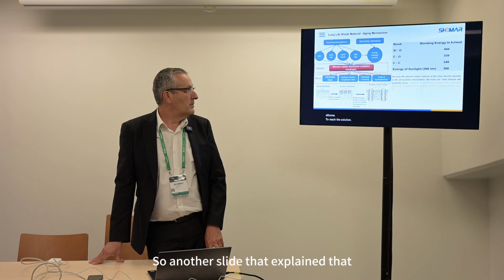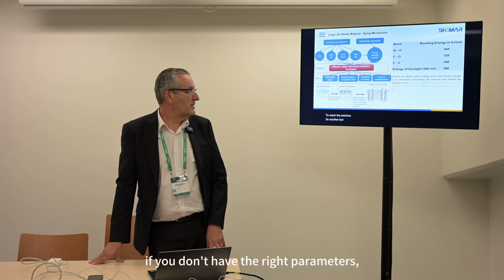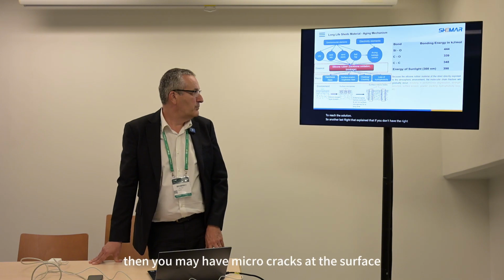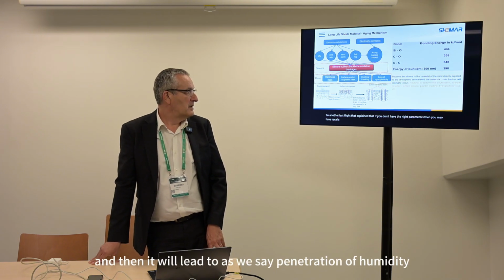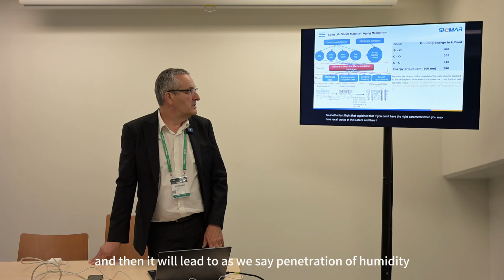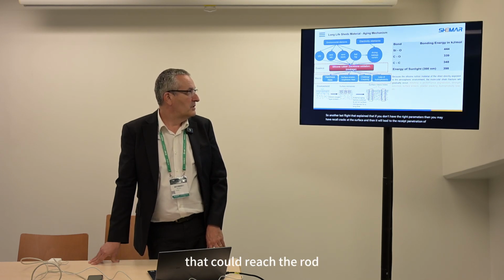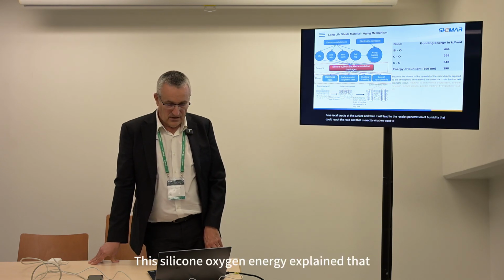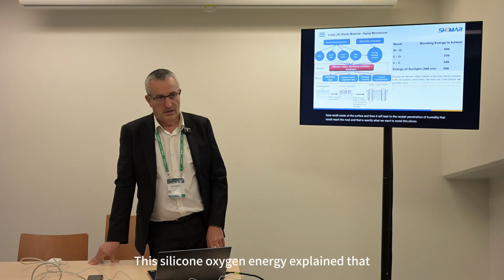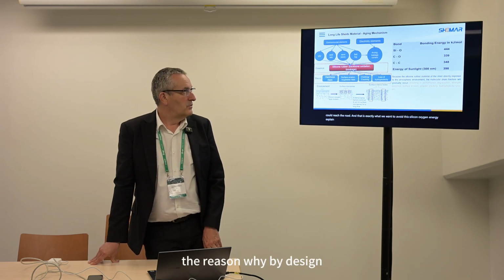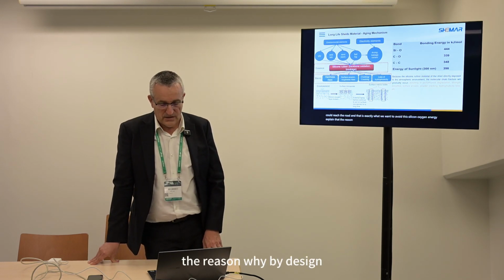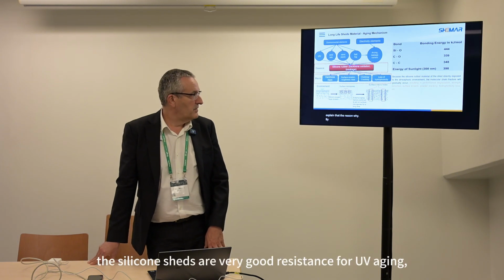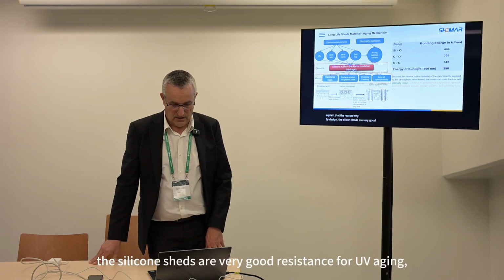Another slide explains that if you don't have the right parameters, then you may have micro cracks at the surface, and then it will lead to penetration of humidity that could reach the rod, and that is exactly what we want to avoid. This silicone-oxygen bond energy explains why, by design, the silicone sheds have very good resistance to UV aging.